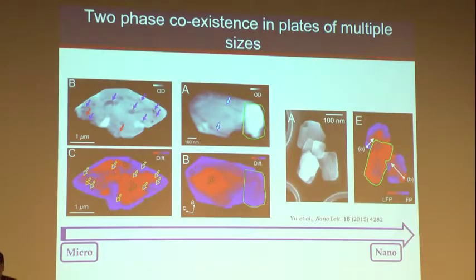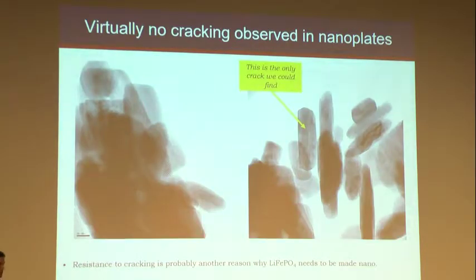We kept pushing the technique. These are images taken at 10 nanometer resolution with the chemistry. And so now we can image true nanoparticles. These are 100 nanometers in the longest dimension. These are the large particles that I showed you in the beginning. That's the one that I was just discussing. These are the smallest ones. These two are fractured. These ones, we looked at hundreds of particles in the TEM, and we could only find one that was fractured. And so we think that that one was already broken when we made it.